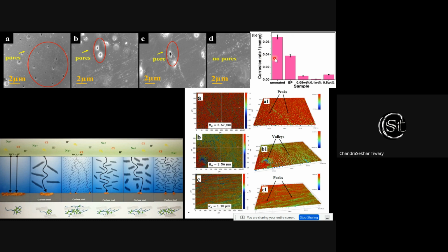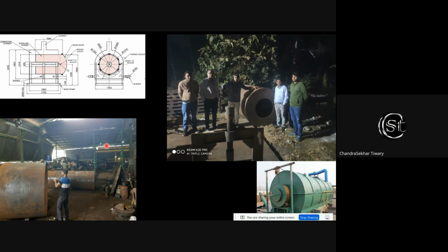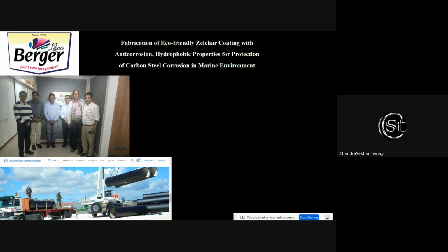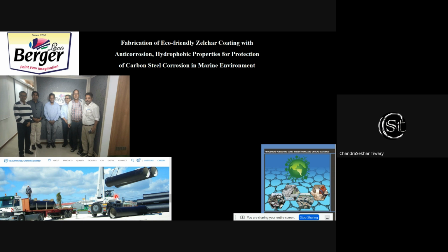The corrosion rate is something which we compared here. This is uncoated steel, the epoxy, and these are different percentages of green graphene, and you can clearly see we observe 3 orders of magnitude difference in the epoxy coating by putting in this green graphene. We also did several other mechanism studies, for example impedance and so on, to try to understand what is happening. At the end of the day, the structure is modified here because of green graphene, which has multiple effects in all our measurements. Hence, currently we are running a 150 kilo per day graphene plant, where we can produce more than 100 kilo of green graphene, which is utilized for paint. We are also looking at water pipes and other structural applications.